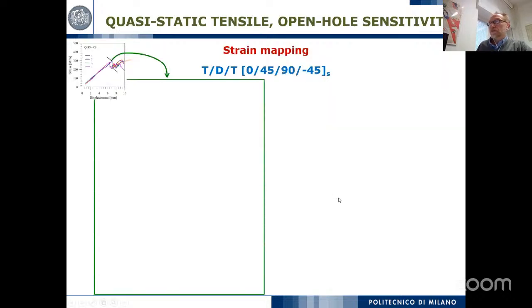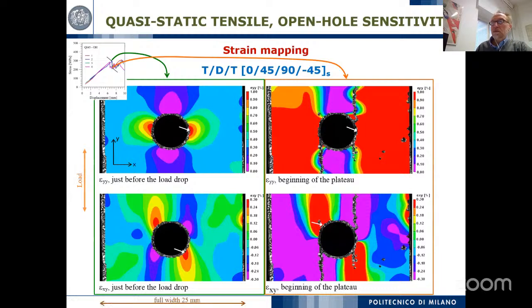It's interesting to observe the damage evolution in terms of strain map that is quite typical in this case for a circular notch, where you have stress concentration at the boundary of the notch. And if you look at the shear strain, this distribution is visible. That is the information we have to understand that the delamination is starting at that position. And this happened for the two different loading scenarios that have been shown here, meaning at the top, at the first fragmentation, and immediately at the beginning of the plateau.